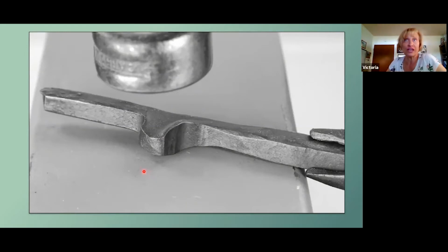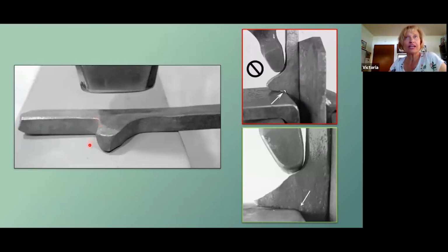When you correct for growth, and that's going to happen, this angle is no longer 90 degrees. It's going to shut down to less than 90 degrees, which means when you put it back in the post vise along the rounded edge of your angle iron, you're going to have a little gap here. When you push down on that, that gap is going to create a little fissure. It's going to close around itself, and that leads to a cold shut, which after you've worked so hard on this tine is going to make that tine fall off and you'll be very unhappy. So make sure that you're always working with a 90-degree angle for that.